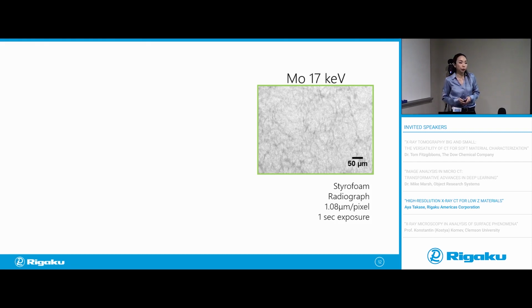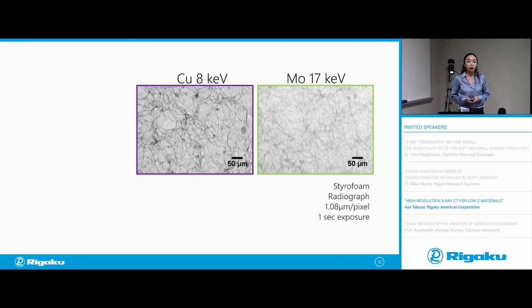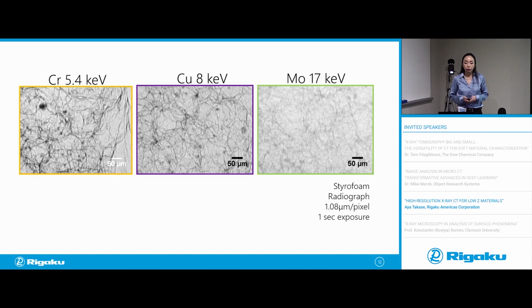If you use copper instead, 8 keV, you can increase the contrast a little bit. And if you use chromium, you can see it even better. So this is just one of the examples where you see the lower energy helps to increase the contrast when you're trying to look at something really light or small.